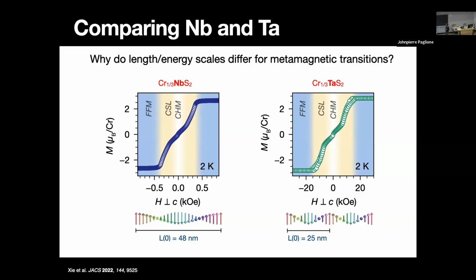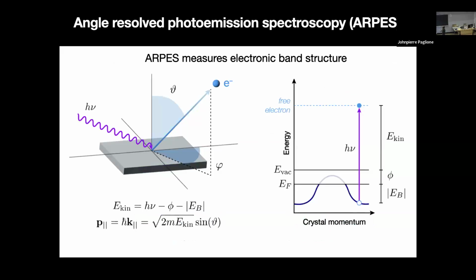But how does that compete with magnetic exchange? That's what we want. Okay, so we want to learn something about the electronic band structure, because then we can model that RKKY term, because we can get the Fermi wave vector. So we can do ARPES, where we get information about the band structure by looking at how a photon kicks out an electron right from the material.